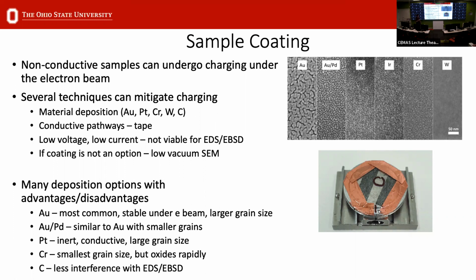I mentioned earlier, sometimes your sample might be in a non-conductive epoxy. In that case, you can use something like copper tape to form a conductive pathway that helps dissipate that charge. In some cases, your material will just charge a little bit, where using the tape to form that pathway will deal with the charging. And we have other talks given previously about low vacuum SEM, which is also a viable option for materials more commonly used in biological samples, but definitely still an option for inorganic samples.